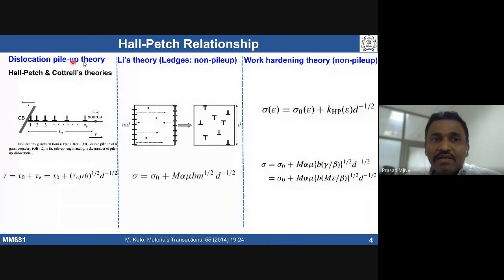So under pile-up theory, Hall and Petch, and Cottrell have given a kind of theory where they consider dislocations getting piled up at the boundary. The dislocation pile-up can burst through after a certain amount of accumulation, or can also initiate yielding in the adjacent grain - the Frank-Read source can be initiated in the adjacent grain because of stress developed. According to Hall and Petch, the dislocation can burst through the boundary. Whereas Cottrell said the stress concentration building up can actually generate and initiate a Frank-Read source in the adjacent grain, then yielding can take place in that adjacent grain also. That's how people have discussed the pile-up theory.